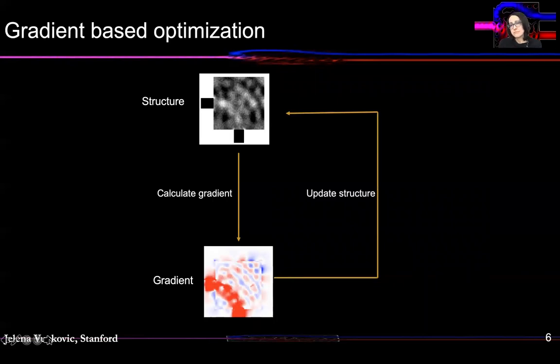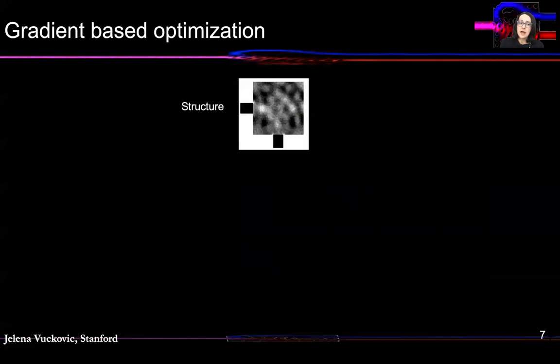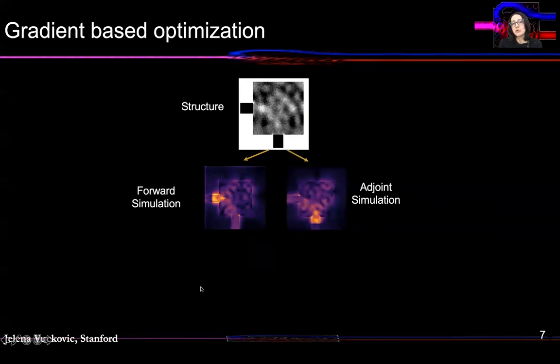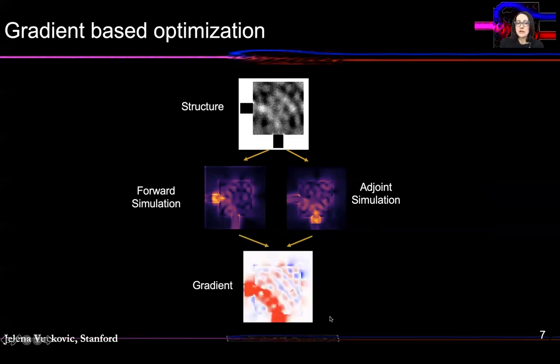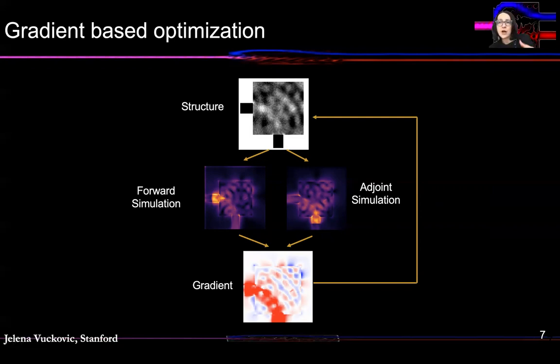Calculation of gradients can be very time consuming, which is why we typically don't do it in a brute force way. Instead, we apply adjoint optimization, which allows us to calculate gradients from two simulations, a forward and a backward simulation of the structure. By combining these two simulations, we can calculate gradients inside of the structure and use that to update the structure in the corresponding way. In other words, by changing the pixels that are most sensitive, we travel in the direction of steepest gradient descent.